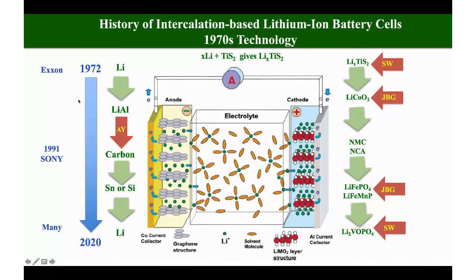When Exxon went commercial, they went to lithium aluminum alloy as the anode because they'd already had issues with dendrites with the lithium. Lithium aluminum is very brittle. It lasts maybe 10 or 20 cycles, and that was enough for the testing they were doing in those days. But it was really Akira Yoshino in Japan who then came up with the idea of using carbons to store the lithium. I show you in this picture, this is graphitic carbon. The challenge here is you need 72 grams of carbon for every 7 grams of lithium. So it's very poor from a weight basis, and the anode takes up half the volume of the battery.